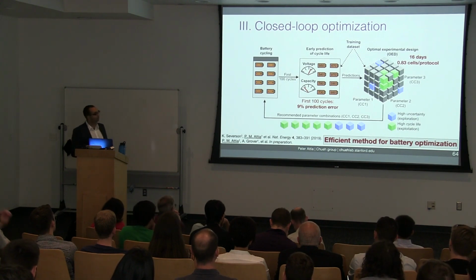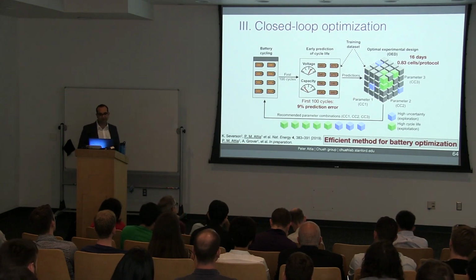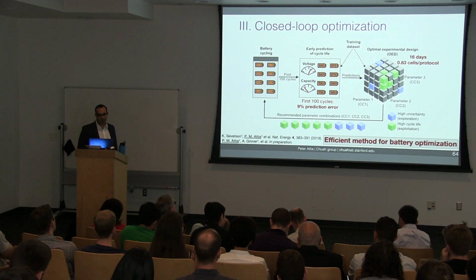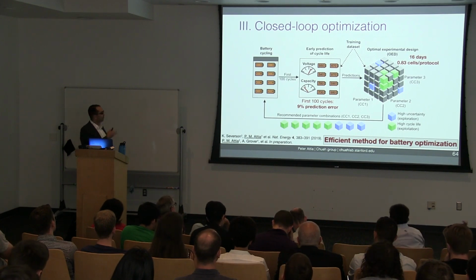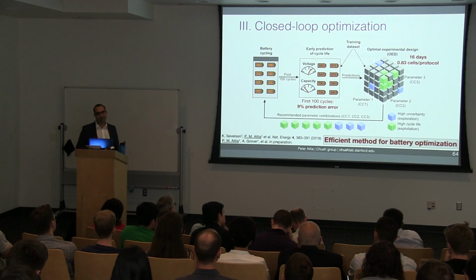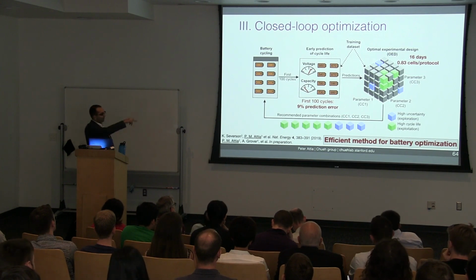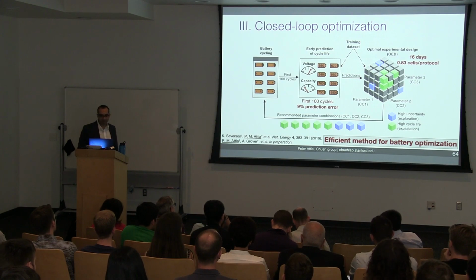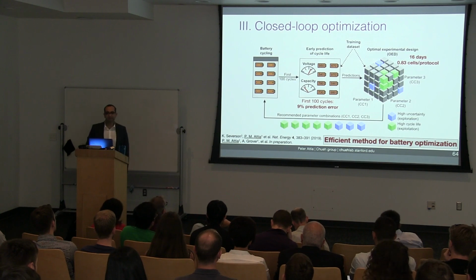So wrapping up part 3, we've successfully demonstrated the power of closed-loop optimization for battery applications such as fast charging. With early prediction, we achieved around 9% prediction error using the first 100 cycles. With OED, we optimized over the whole parameter space in 16 days using less than 1 cell per protocol. Again, it's a combination of these two elements that makes for a unique and powerful method to accelerate battery development.